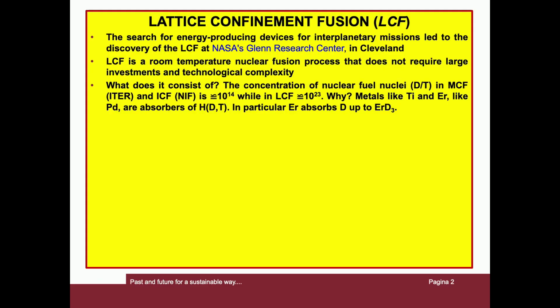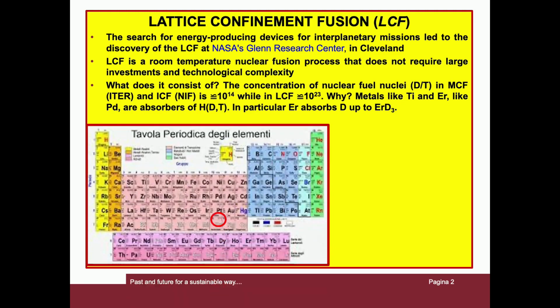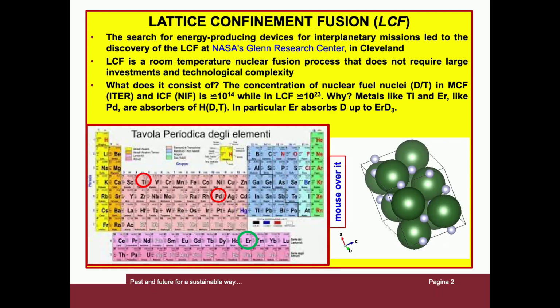The search for energy-producing devices for interplanetary missions led to the discovery of lattice confinement fusion at NASA Glenn Research Center in Cleveland. Lattice confinement fusion is a room-temperature nuclear fusion process that does not require large investment and technological complexity. What does it consist of? The concentration of nuclear fuel nuclei in magnetic confinement fusion and in inertial confinement fusion is about 10^14, while in lattice confinement fusion it is about 10^23. This is practically the Avogadro number. Why? Metals like titanium and erbium, like palladium, are absorbers of hydrogen and its isotopes. In particular, erbium absorbs deuterium up to ErD3.